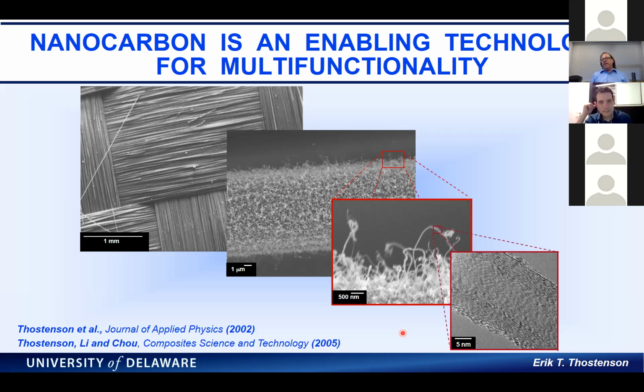But I think there's room for improvement. It wasn't so much growing these little hairs, or the fuzzy fibers, as we called it. And it wasn't like pulling a tree out of the ground with all the roots. I did a quick model, and if you predict what the shear modulus increase should be, it was pretty consistent with what we would expect. We did fiber fragmentation, and that changed the fragment length. So it was really more of a stiffening of the interface.